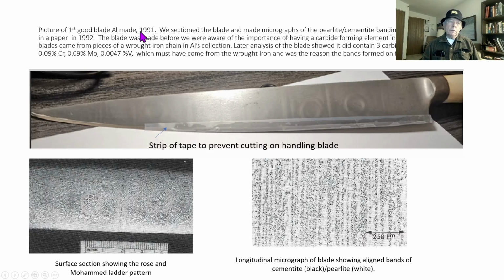In 91, Al made this blade, which he gave to me. There's a piece of tape down here that I put on so you wouldn't cut yourself. On the blade, you can see the Damascus pattern and the rose pattern and the regular pattern in between. We sectioned this baby and made micrographs of the pearlite cementite banding that we found, and it lines up pretty well. This is what the surface looks like, showing the two types of patterns, the rose and the Mohammed.